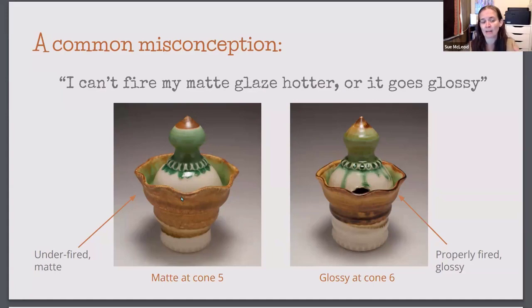When your glaze is underfired, it means it hasn't melted and fused into a glass, and the glass is not very strong. Underfired glazes are not very strong. They're not fully matured yet, so they're vulnerable to acids and bases and dishwashers and cutlery. You really want your glaze to be well melted in order for it to be durable. So if you have a matte glaze that goes glossy when it's fired hotter, I would look at the chemistry of that glaze. Is it a true matte glaze? If it doesn't fall in the matte region of the Stull chart, it could be just an underfired glossy glaze, and then you might want to take a look at that.